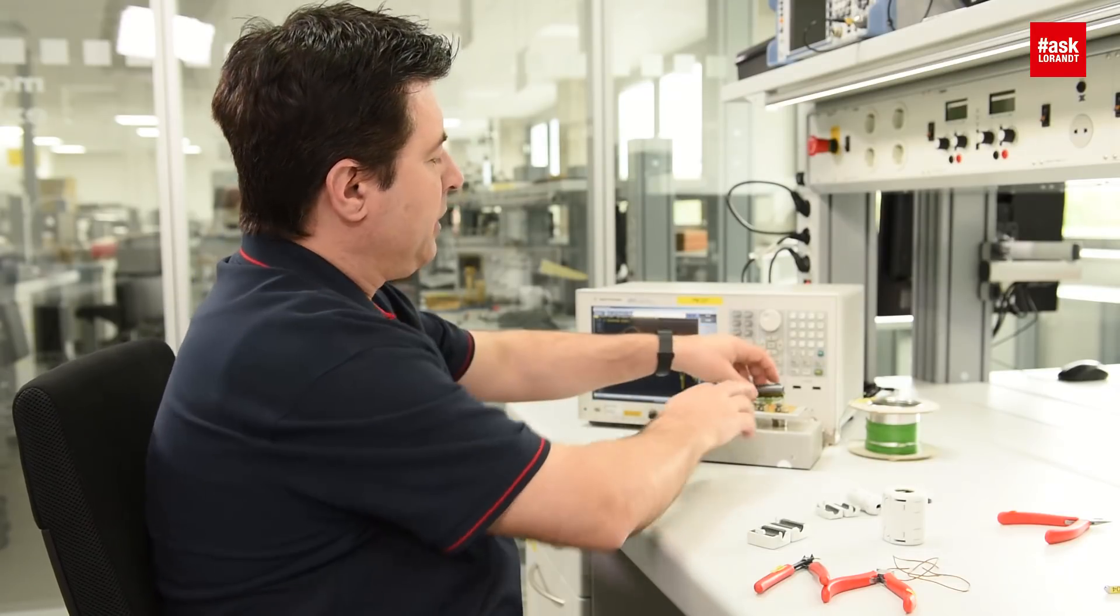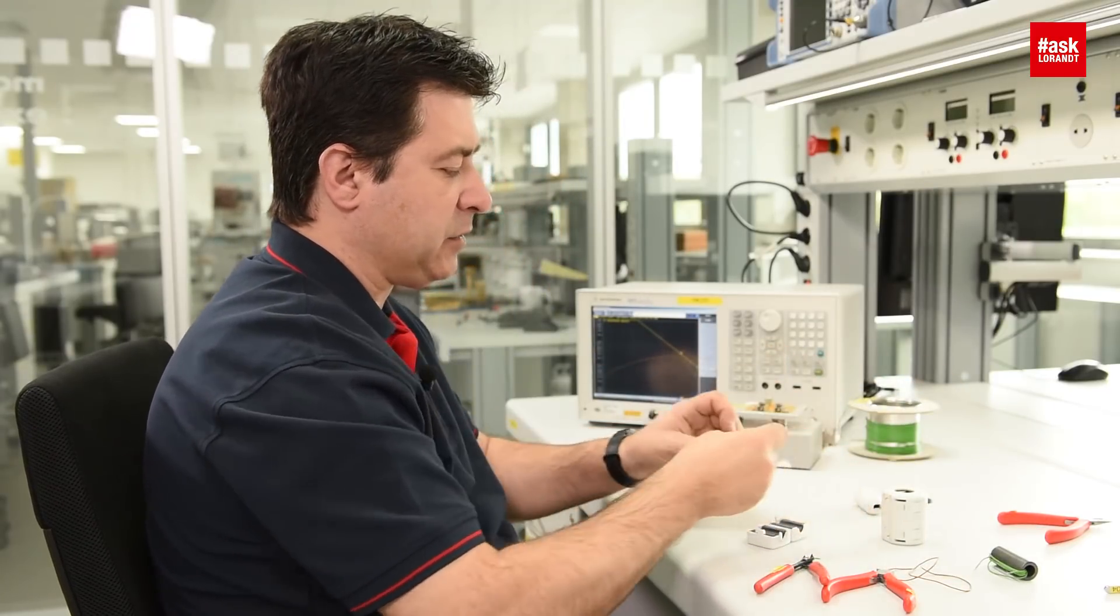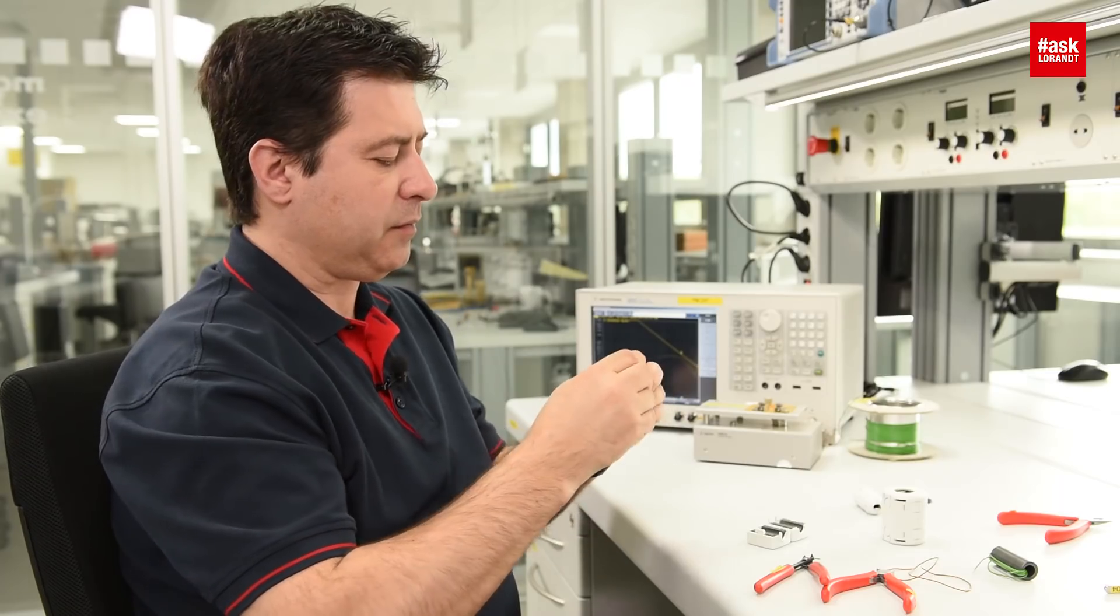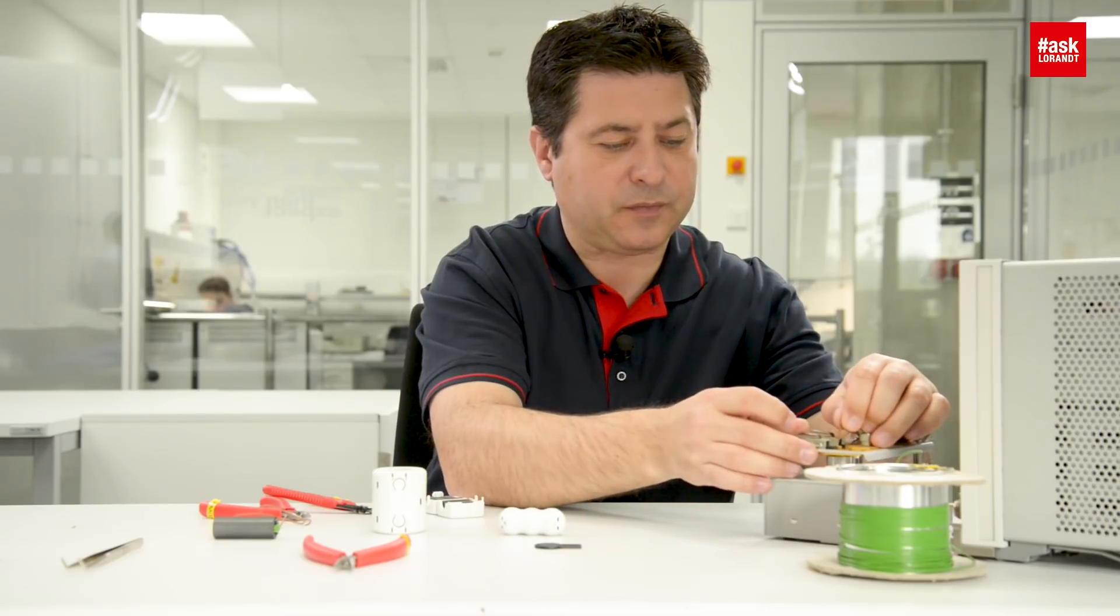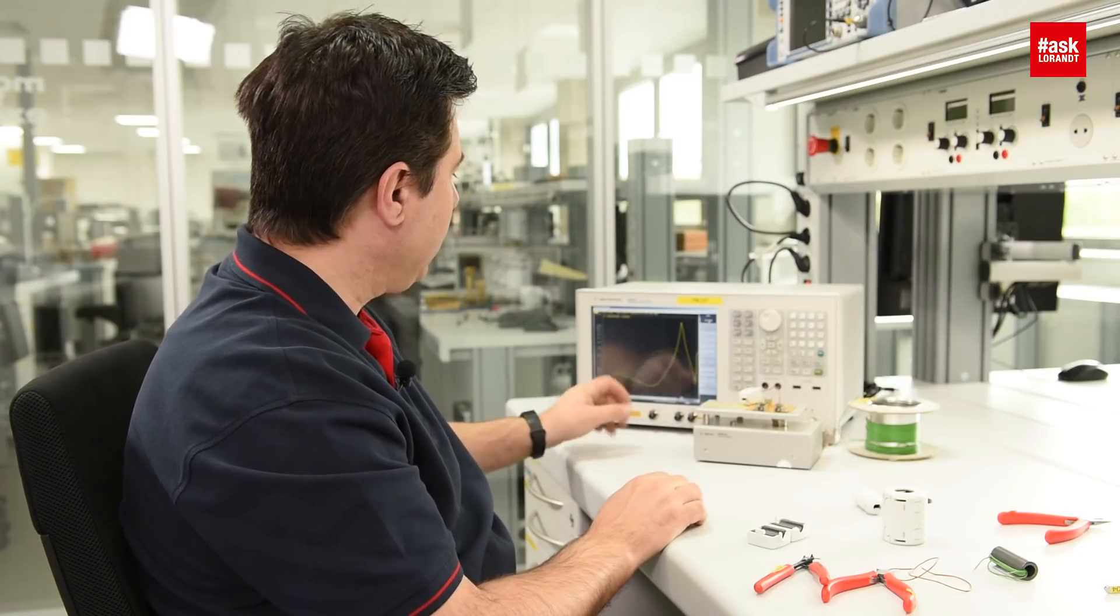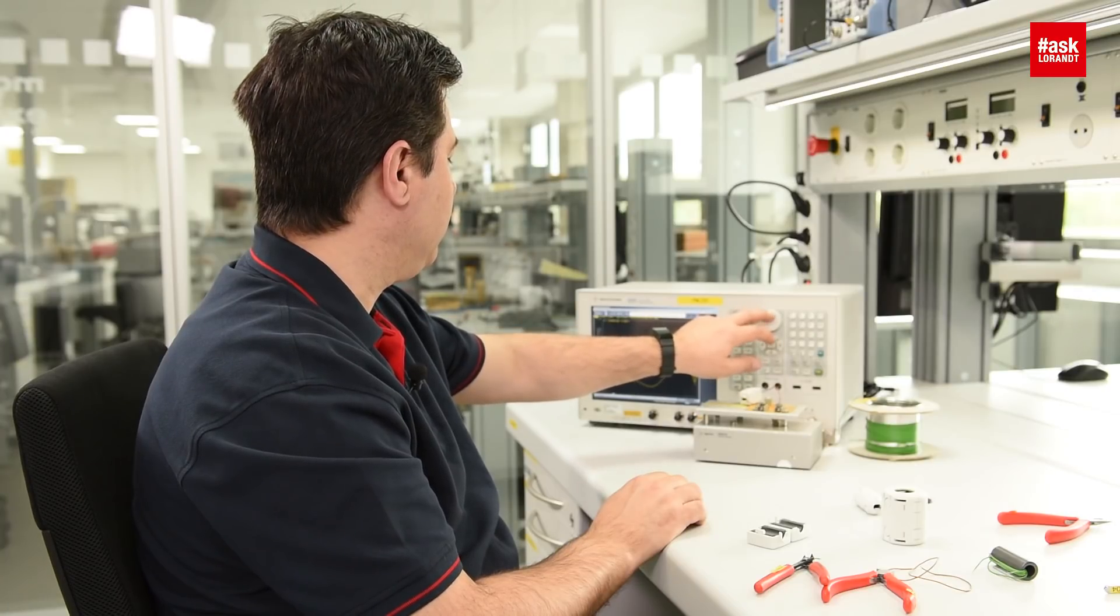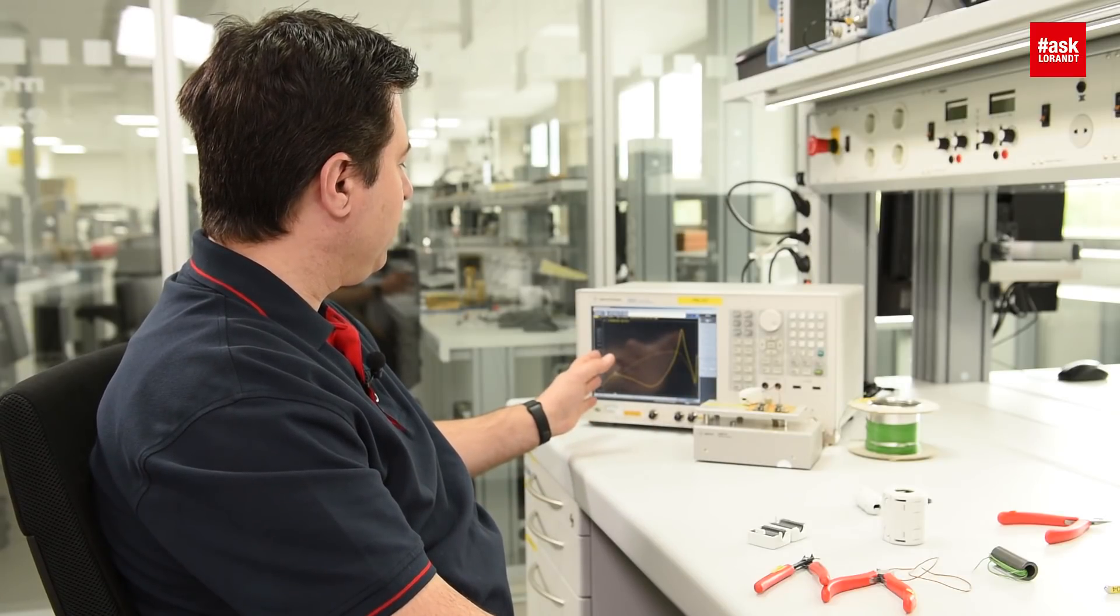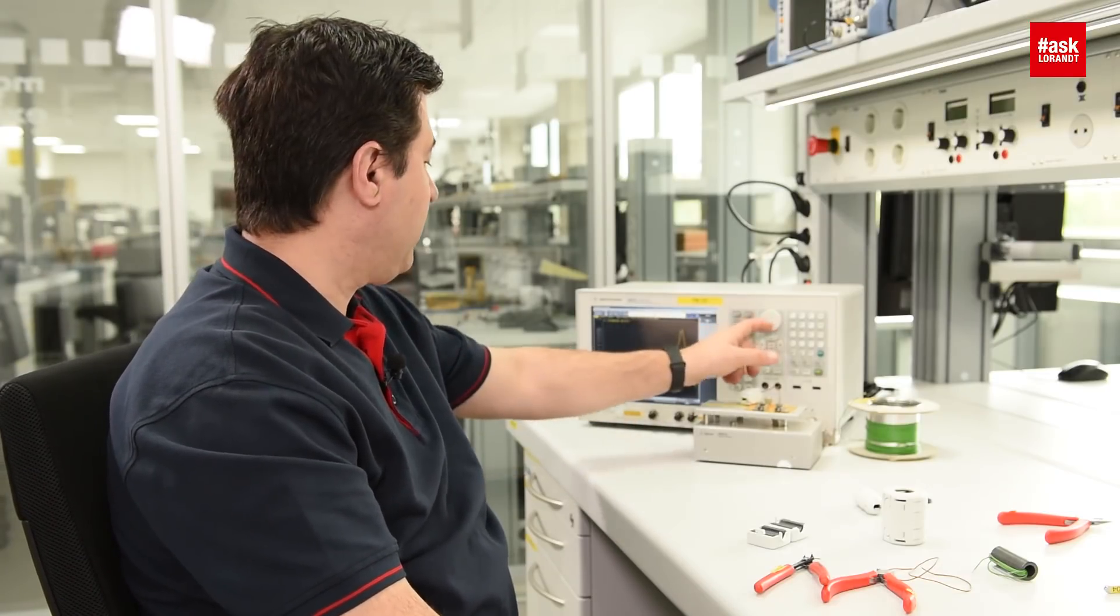What you can do, you can compare this now with many turns with one different ferrite core that we have in manganese zinc. Because all these ferrite cores were using nickel zinc. And now if I compare that with a manganese zinc core. With a manganese zinc core, you can see that in low frequency, you have already high attenuation. Much higher attenuation already at 2.4 megahertz or 5 megahertz. You have excellent attenuation by using a manganese zinc core. But for high frequency, you will lose them.